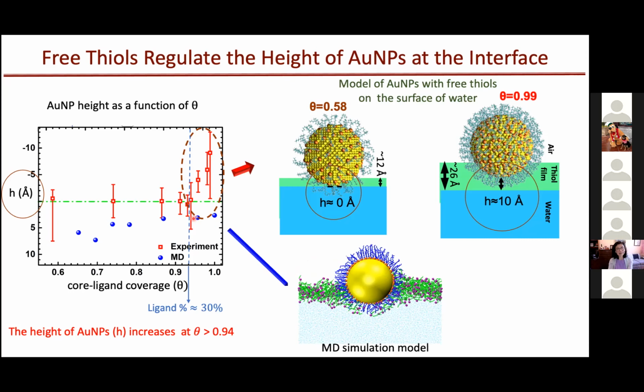But that could be due to the fact that in our simulation, the gold core was modeled as a sphere instead of a polyhedral gold crystal with flat facets. We know that these thiols are more ordered on flat surfaces.